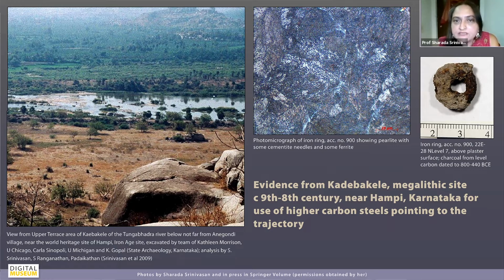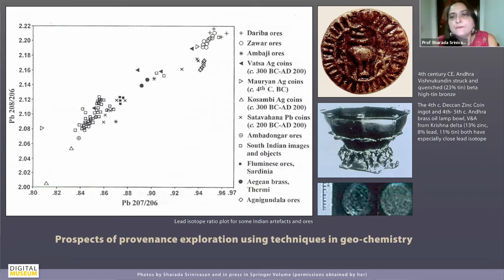This also takes a lot of work to unpack, but I'll just point to a couple of examples where one can use, for example, the technique of lead isotope ratio analysis for provenancing some artifacts, because basically lead has this characteristic that the isotopic ratios vary distinctly and measurably across different ore sources. And also, the lead which is used in an artifact, unlike the trace elements and so on, the isotopic ratio remains the same from the ore to the artifact. So basically, if the lead isotope ratios of an artifact match a particular ore, it's very likely that it's coming from that ore source. So it's a way of provenancing the artifacts.